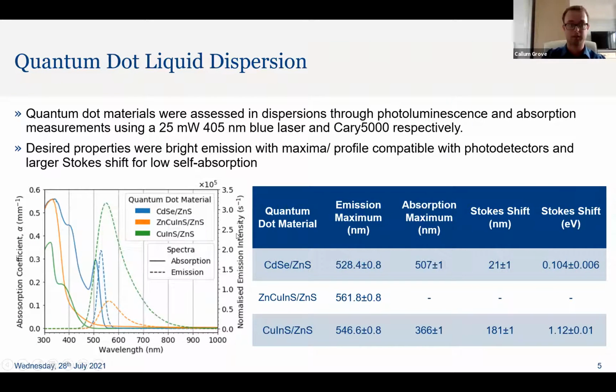So as I said, we had a quantum dot liquid dispersion test. We dispersed 5 milligrams of these quantum dots into 5 milliliters of toluene, and then we did an emission study using a 405 nanometer blue laser, and an absorption study using a Cary 5000 spectrometer. So we have various emission maxima that are presented in both the table and the plot on the left here.